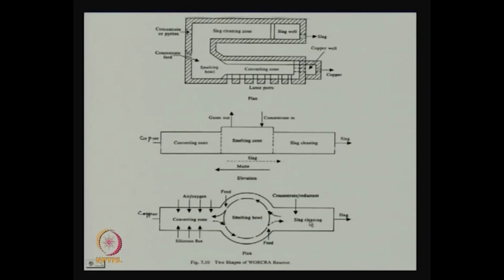If there is some Cu2O, you must get that copper out by reduction. So, here our PO2 level has to be very low, here it is the highest, here it is intermediate. Now, how do we ensure that copper and slag move in the other direction?